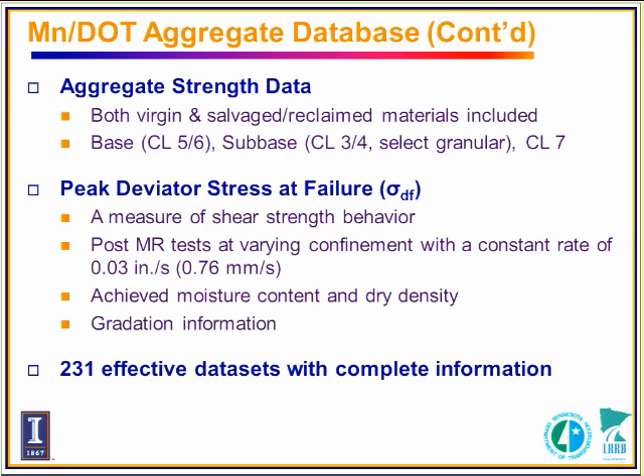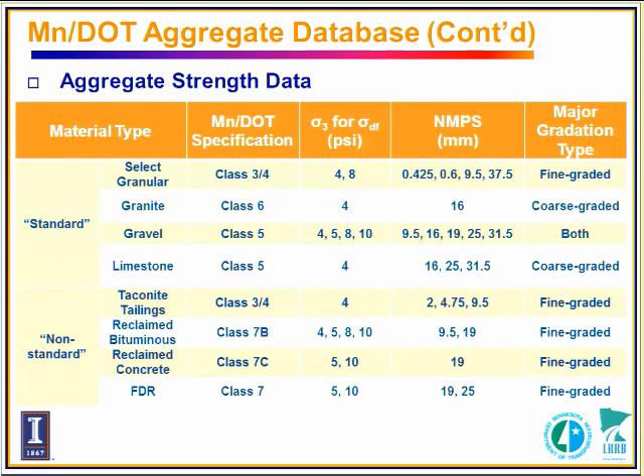They also have the shear strength test results. Basically, at the end of the resilient modulus test, they failed the sample to collect the peak deviator stress at failure. And this table just summarizes the information about the materials we collected for the shear strength analysis. As you can see, there are two categories, standard materials and non-standard materials, different classes, and different confining pressures for the peak deviator stress at failure.